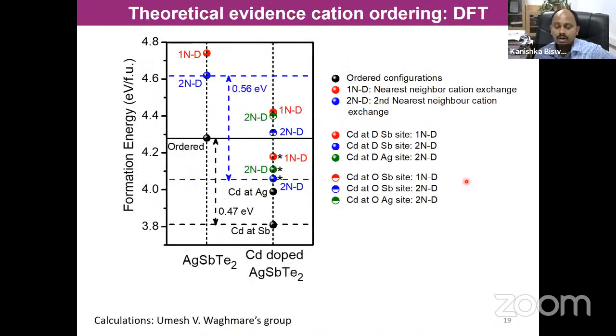Now we have collaborated with our theoretician colleague, Professor Umesh Waghmare in our institute, who showed by formation energy calculation that the ordered AgSbTe2 is a lower energy structure than the first nearest neighbor and second nearest neighbor structures, which were predicted by Mohanty in 2007 in his PRL. As soon as we dope cadmium, the cadmium doped ordered structure is an even more stable structure. So that's the indication. There is a lot of information from this plot. I have no time to tell in detail.